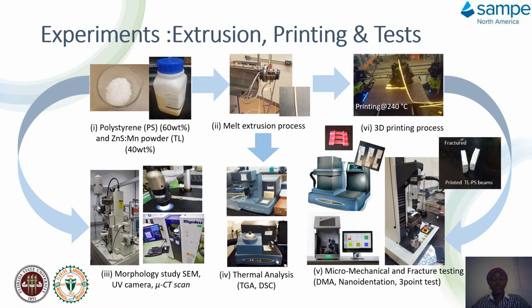So these three processes were examined using the SEM and CT scan to show how the TL crystals break down from one process to the second process to the third process. Then after that, thermal analysis was carried out to show the thermal stability or thermal degradation that affects the material when processing in the extrusion.